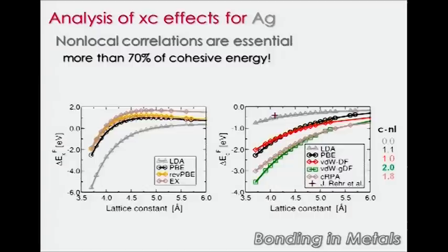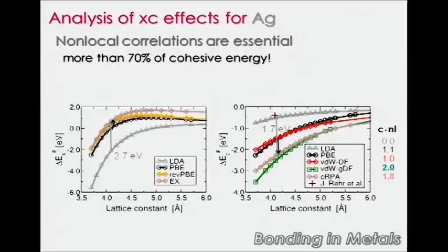We could analyze this by looking at the different contributions for exchange and correlation separately. And what you see here, of course, is the error cancellation effect. For instance, if you count now the error of LDA with respect to exact exchange, it's 2.7 electron volt. If you look at the error in the correlation, it's minus 1.7. So these 2 effects cancel each other. So in general, we know already, but in general, DFT results are not so bad. The error is smaller in PBE. So this is the exchange part, this is the correlation part. Of course, we shouldn't compare exchange and correlation separately, but what we can learn from these figures is how important non-local correlations is.